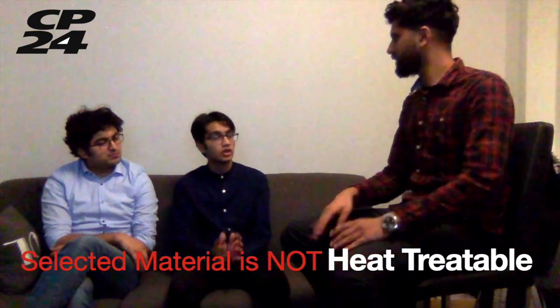Actually, for this it doesn't apply because austenitic stainless steels cannot be heat treated. Why is that? Austenitic stainless steels have a face-centered cubic crystalline structure with a high level of chromium. At high temperatures, the formation of chromium carbide at the austenite grains results in the decrease of the chromium content in these grains, resulting in the removal of the protective passive film. This process, which is called stabilization, involves the formation of preferred carbides compared to the chromium carbide. So austenitic stainless steels cannot be heat treated.